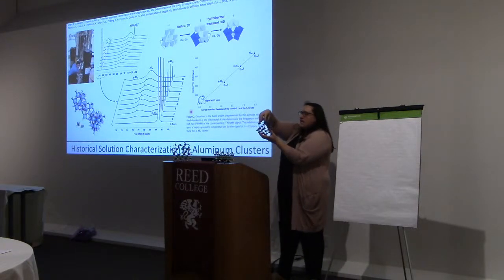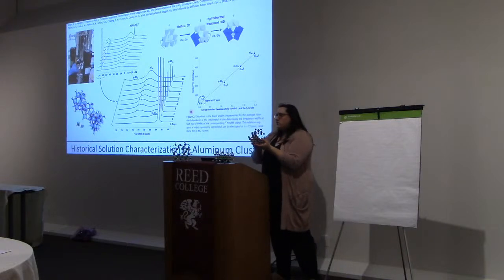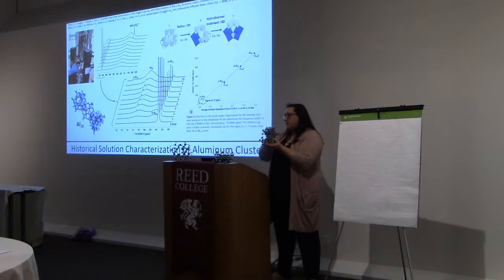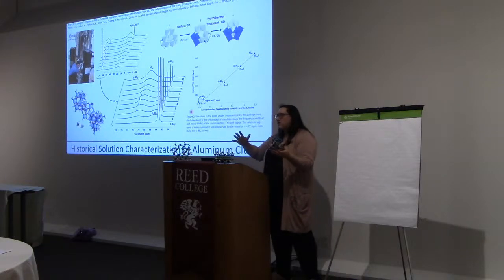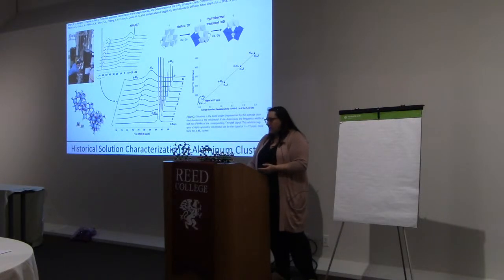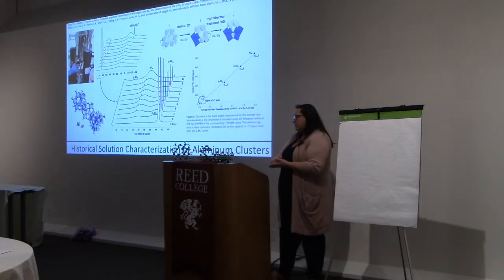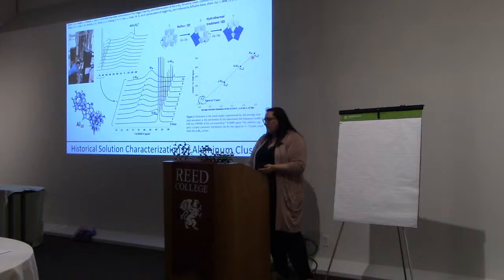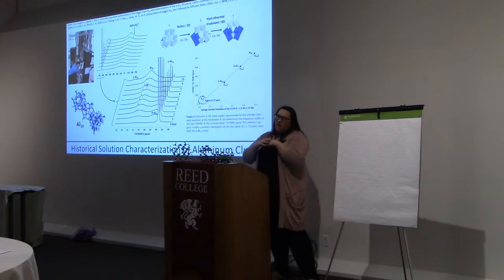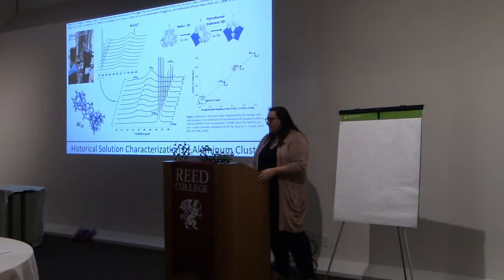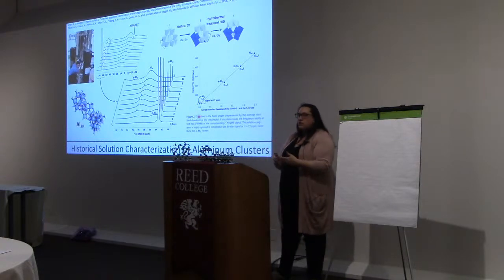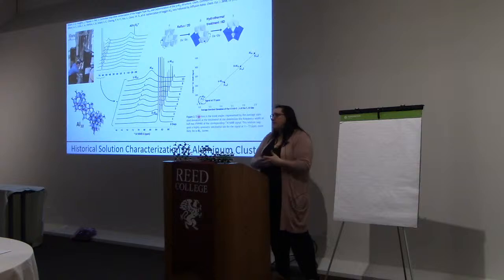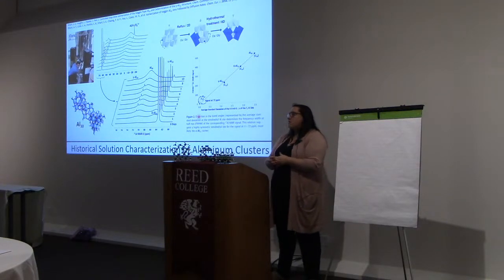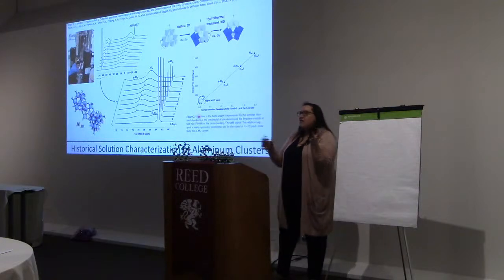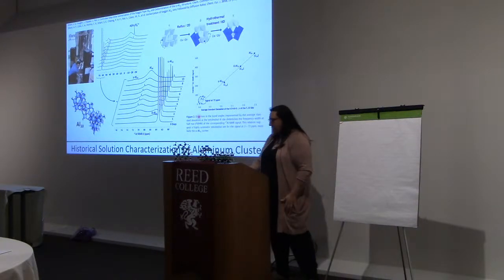as you rotate these and break the symmetry, your tetrahedral site does not have the same bond angles. It gets distorted, and so you get these broader and broader signals. Those sharp signals in the tetrahedral region, like our epsilon, are only coming from the most symmetric version. And so I looked at the bond angles and found the standard deviation of the bond angles around the tetrahedral site and kind of related that to then the width at half max of these signals, and we were able to see that the only cluster that's known that could have corresponded to was that alpha. And so we were able to then publish that we saw that alpha in the signal, and it was the first time outside of the mineral zunyite that the alpha isomer with aluminum had been detected.